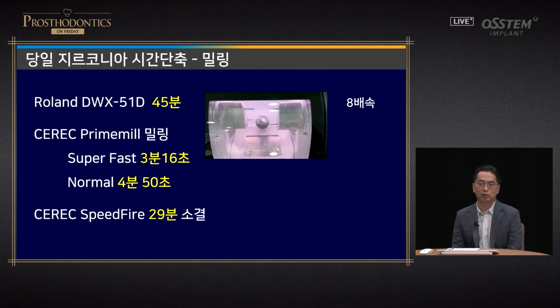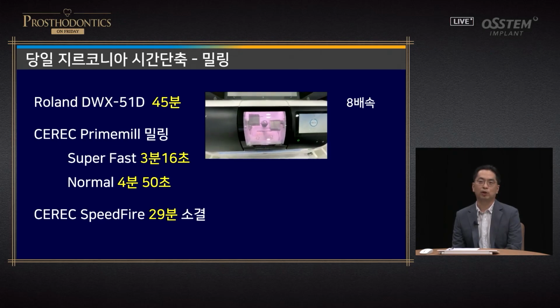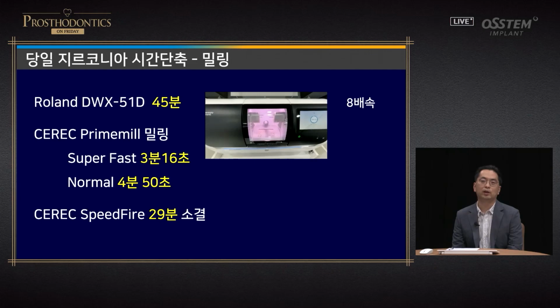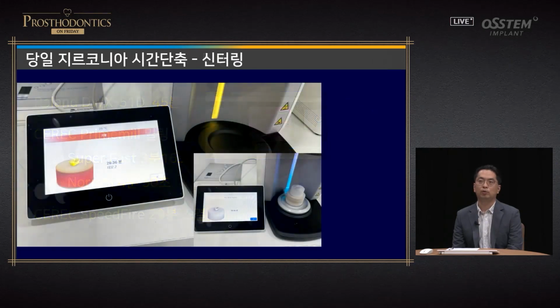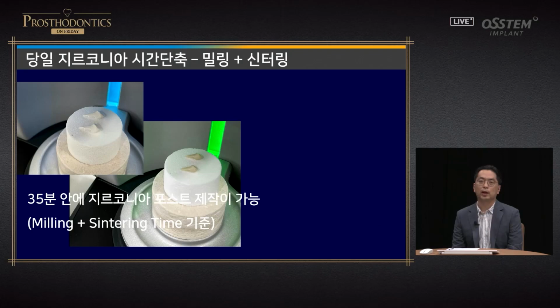In super fast mode, I can fabricate post-core in 3 minutes 16 seconds. In general mode, it's 4 minutes and 50 seconds. In CEREC Speedfire, zirconia post and core can be sintered in 29 minutes. Within 35 minutes, zirconia post was fabricated. In doing one-day zirconia restoration, it is very important to reduce milling time.